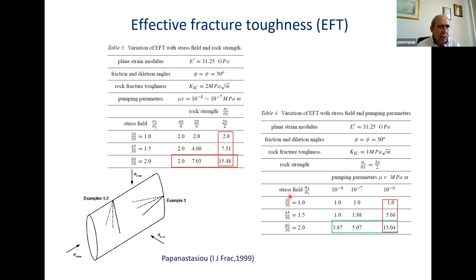In the second example, what we varied, we kept the same rock strength ratio, compressive to tensile, as you can see, and we varied the pumping parameters in the columns, and again, different stress field in the rows. Again, you can see here, of course, when we have high pumping rates, we get higher stress concentration and more plasticity, but this effective fracture toughness is particularly high when the stress field is anisotropic. That's the case when the front propagates vertically.